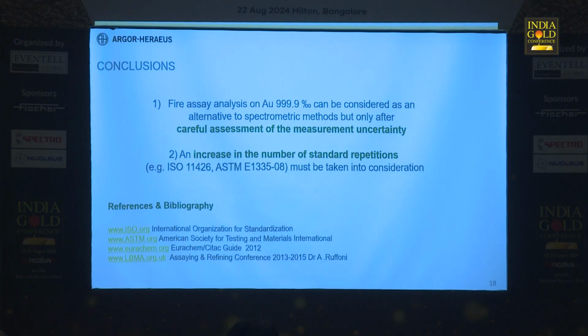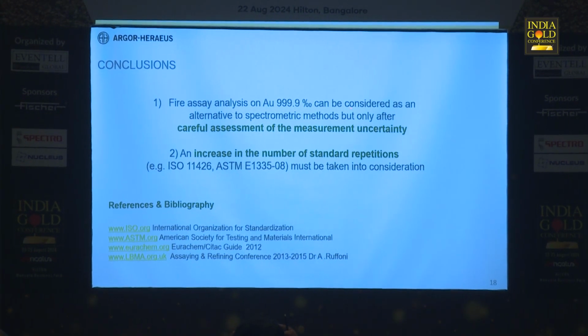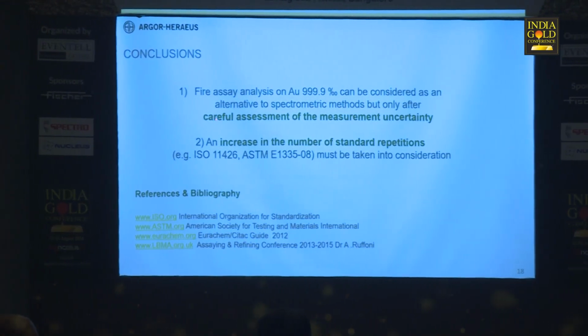So the conclusions are these. The fire assay on Au 999.9‰ can be considered as an alternative to the spectrometric method, but only after a careful assessment of measurement uncertainty. The other conclusion is that an increase in the number of standard repetitions must be taken into consideration. With respect to these two normatives that I took into consideration.